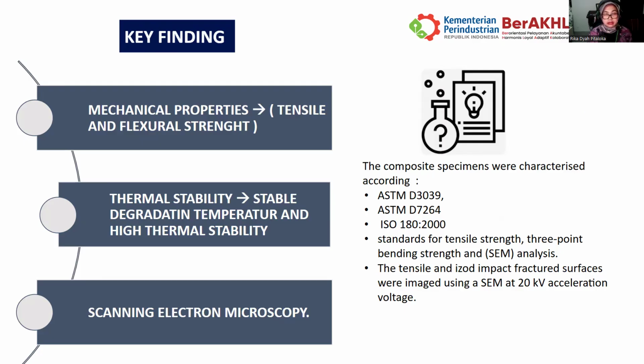Another key finding is about the thermal stability. The composite is expected to exhibit high thermal stability, with a char yield around 99% and a stable degradation temperature. There is also the dynamic mechanical analysis, which shows an increase in the storage modulus and a decrease in the damping factor with higher fiber contents, indicating enhanced stiffness and elasticity.